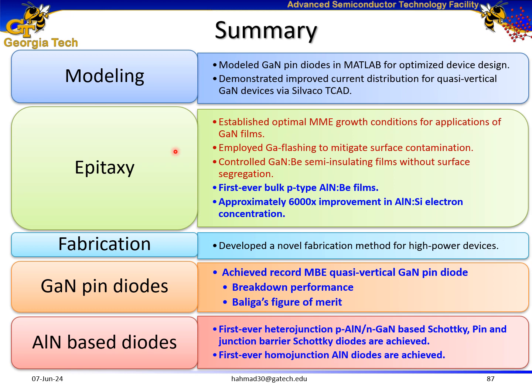I've achieved approximately 6,000 times improvement in electron concentrations in silicon-doped aluminum nitride. From fabrication perspective, I've developed a novel fabrication method for high-power devices. I've achieved a record MBE quasi-vertical breakdown performance and also Baliga figure of merit for gallium nitride PIN diodes. I've achieved the first ever heterojunction p-type aluminum nitride on n-type gallium nitride based Schottky PIN and junction barrier Schottky diodes. I've achieved the first ever homojunction aluminum nitride.